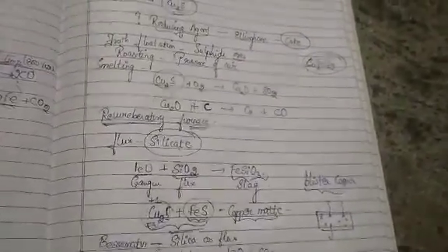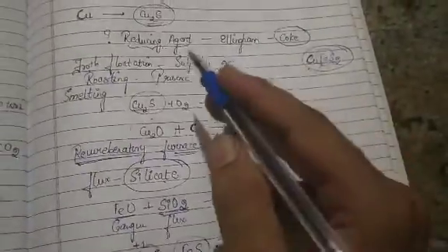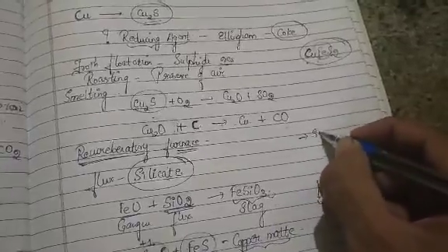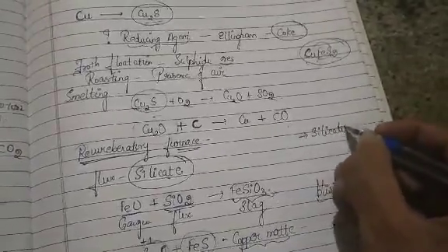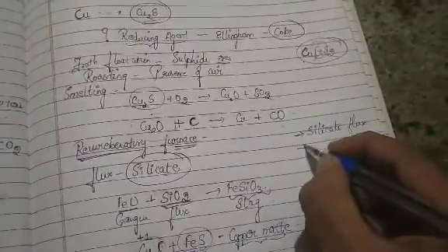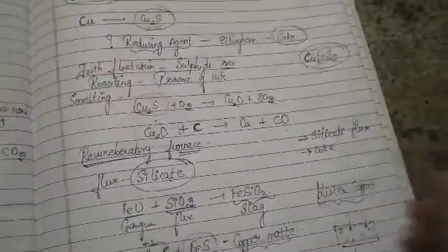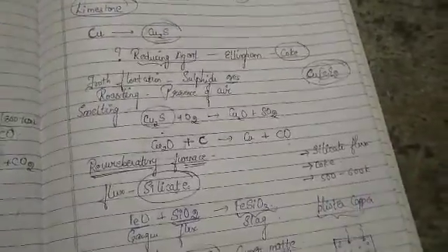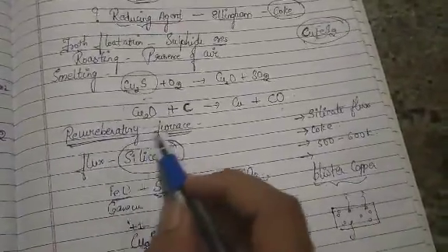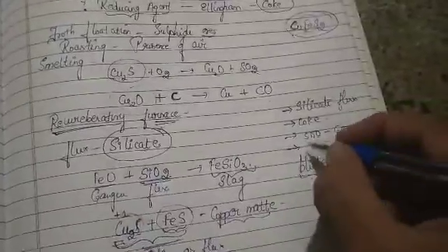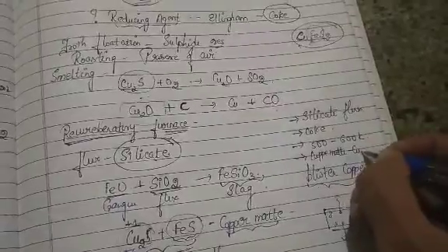But do remember, a major important thing. During the extraction of the copper from copper pyrites, we have seen that the first part is you have used silicate as a flux, whereas you have used coke as your reducing agent. Temperature you have maintained nearly 500 to 600 Kelvin. And whatever copper you have obtained in a reverberatory furnace is not the purest copper. Instead, it is in the form of copper matte, that is, you are having the composition of Cu2S plus FeS.